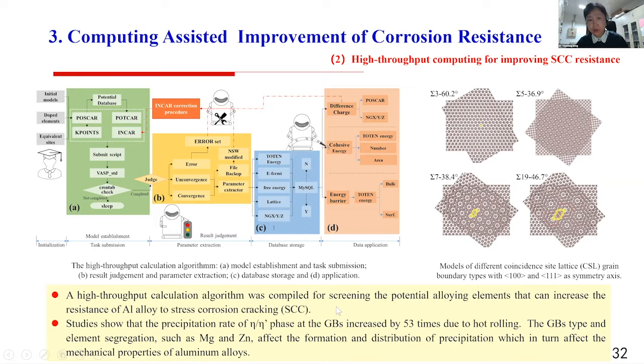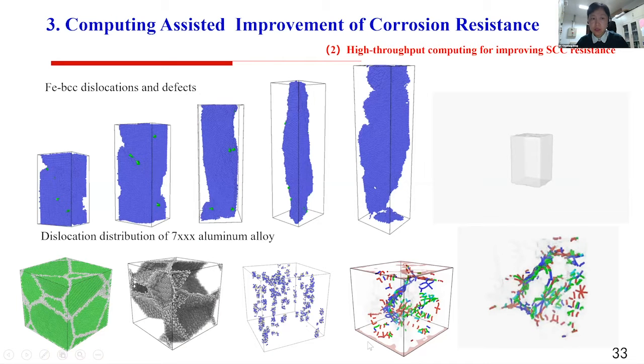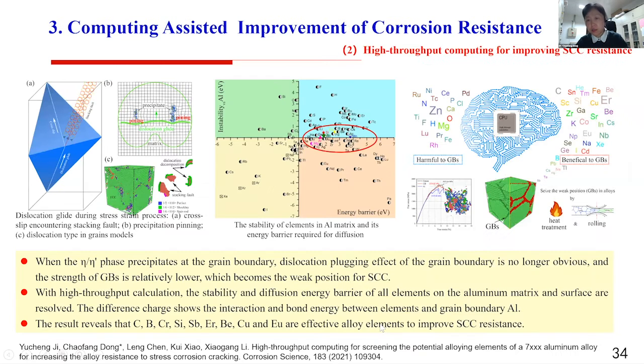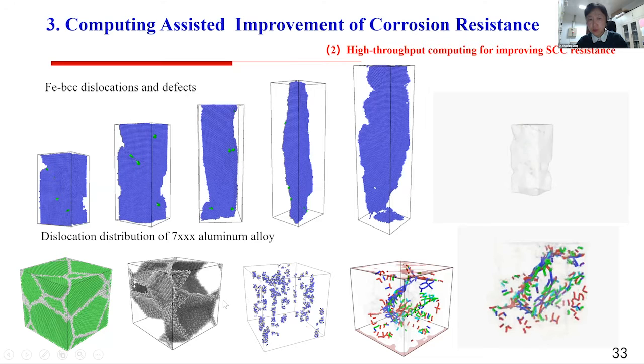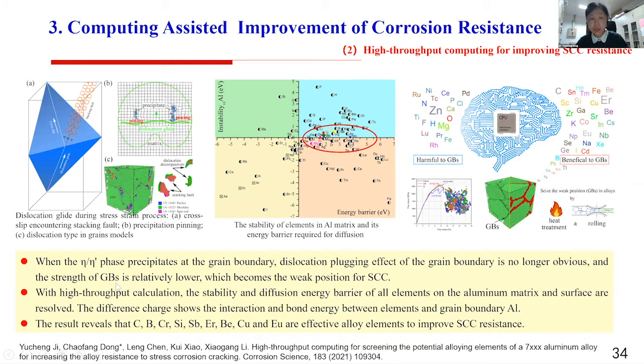We just use it to screen the potential alloy elements that can increase the resistance to stress corrosion cracking. This one is about the different kinds of dislocations moving, so we can investigate the grain boundary and also the interaction. For example, the eta and eta prime phase precipitate at the grain boundary, the dislocation